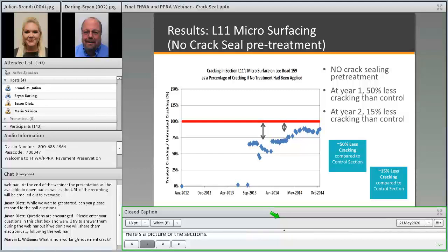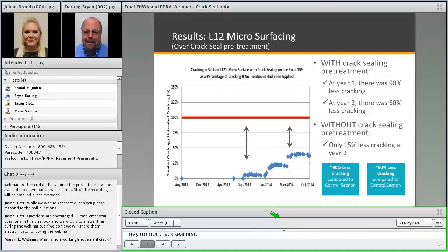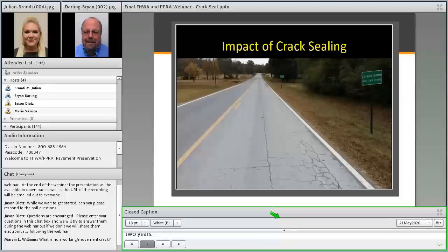This section was a micro surface. They didn't crack seal first, went down, and put down a micro. After 1 year, there was about 50% less cracking in comparison to the control section. After 2 years, only about 15% less cracking. And then in section L12, they crack sealed first as a pre-treatment and then applied the micro. And we saw better performance of the microsurfacing. After year 1, 90% less cracking, and at year 2, 60% less cracking.